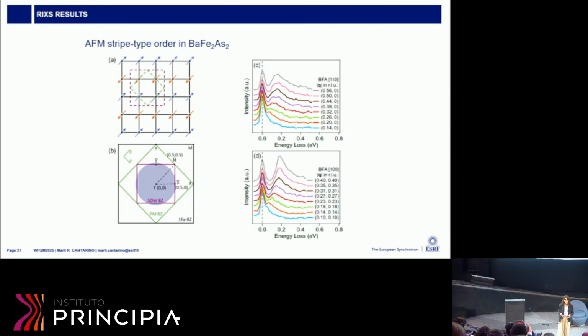So this is now the results of the manuscript, which you could probably read tomorrow. What we see is that for the parent compound, as I mentioned, we have this stripe type order. With RIXS, we can probe this blue circle here, so we have access in reciprocal space to the ordered Brillouin zone.